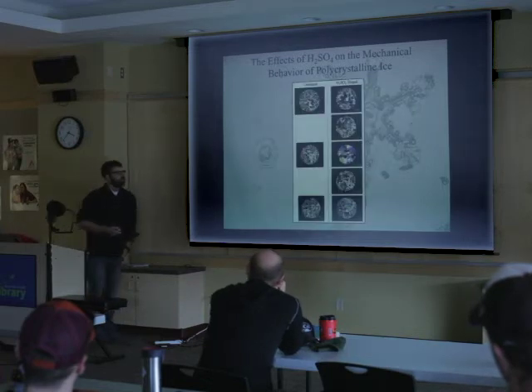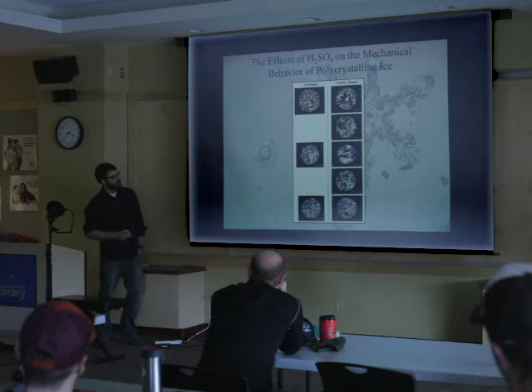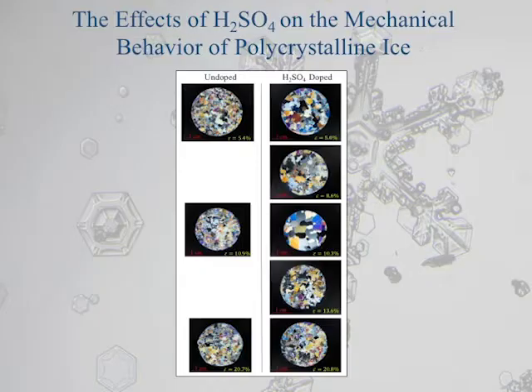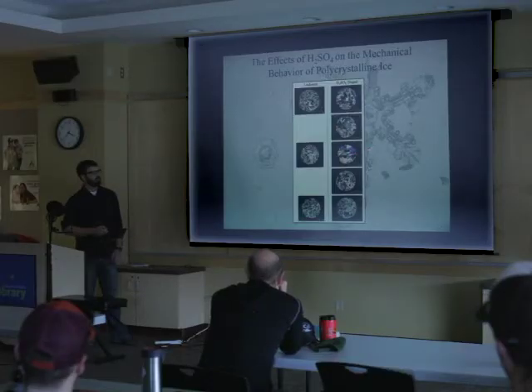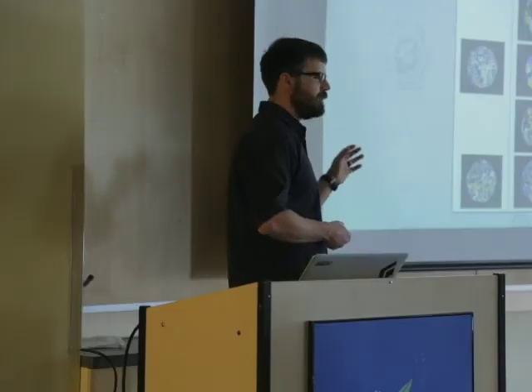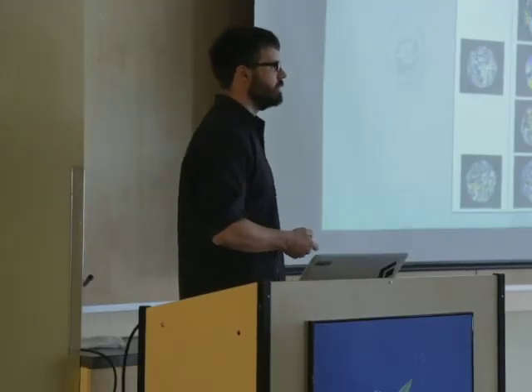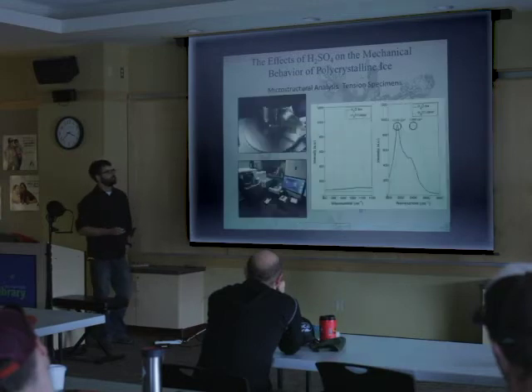We look at the microstructure here, completely different. So this is at around 10% strain for a sulfuric acid doped piece of ice and a non-doped piece of ice. And what we saw is these grains grew to be much, much larger than these, by like a factor of 2 or 3. And so that is going to link us back to the type of deformation that was happening, the mechanism by which the molecules are rearranging themselves, more or less, in the solid is related to what you're seeing here in the different sizes of the grain. This is, again, I'm just going to stress this, like 10 parts per million sulfuric acid that we put in here, so not very much, has a dramatic effect.